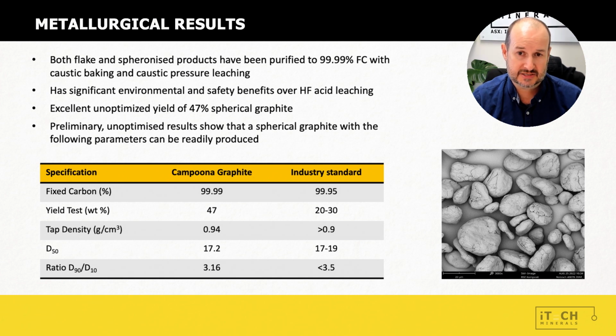Now, our preliminary unoptimized results show that spherical graphite has really favorable industry standard parameters. So the fixed carbon content was 99.99%, well above the industry standard of 99.95%. Our yield test was 47%, and this is an unoptimized yield, so we hope to get that higher. But that is well above the industry standard of between 20 to 30% that you get in China.